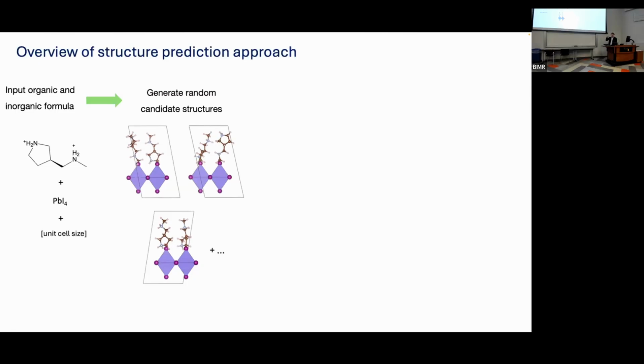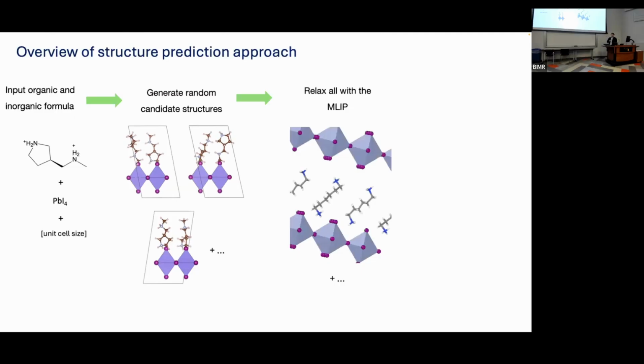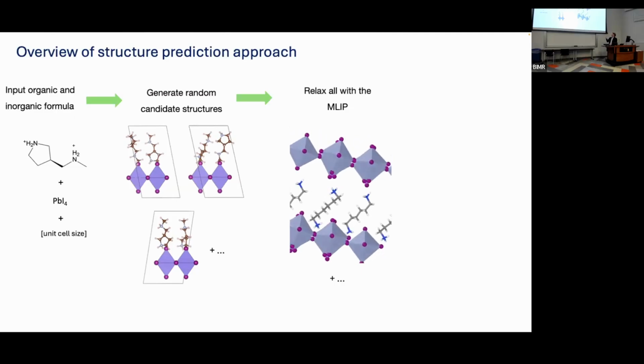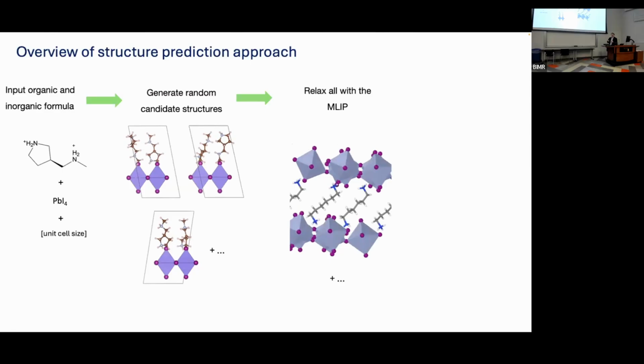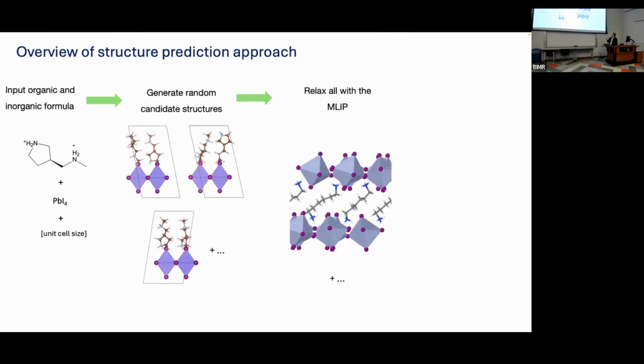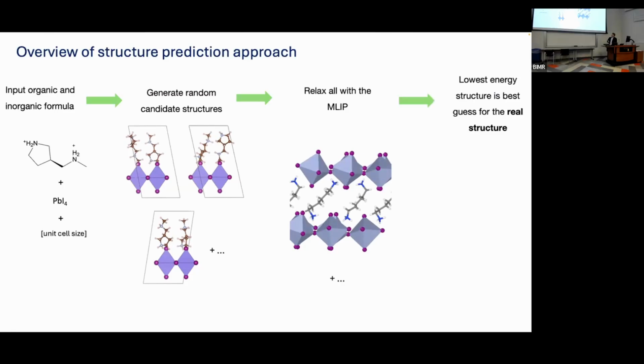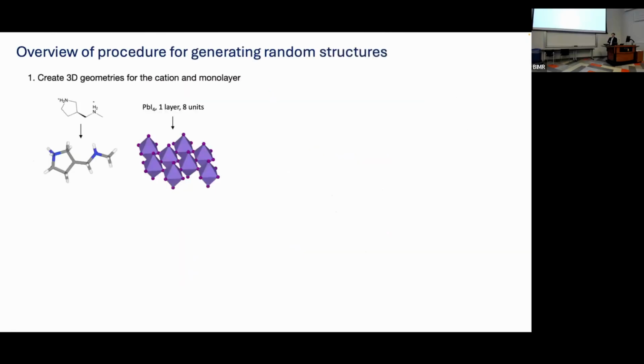And then we apply it to this large set for any given organic molecule. And that gives us pretty bad structures. But because we have energies and forces trained in our model, we can then optimize them subsequently. And that's what you see. You start from a bad guess. The stochastic sampling algorithm isn't that good, and it's sort of a brute force approach. But we rely on the fact that the MLIP is very cheap, and so we could give it a bad guess and still optimize to something that looks reasonable. And then we could do this over and over for many different permutations of the organic slab, and just rank these all by energy. And the lowest one becomes the one that we think is the ground state.